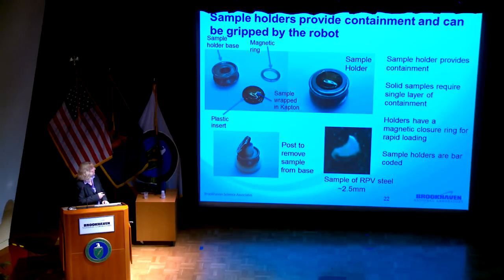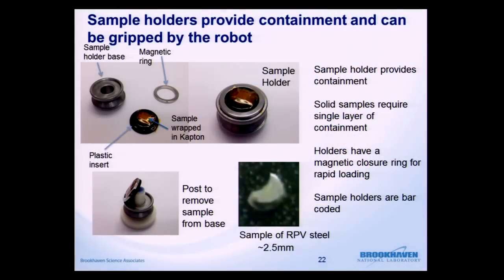These are the sample holders that we designed for radioactive materials. This is one of our samples. This is a sample of reactor pressure vessel steel. It's only 2.5 millimeters at the maximum, and it's just about a millimeter thick. So our users have to wrap the sample in this orange tape. It's about the consistency of Scotch tape. You wrap the sample in one layer of Kapton tape and then stick it to a plastic ring. And then they can ship the ring to us with the sample in it.